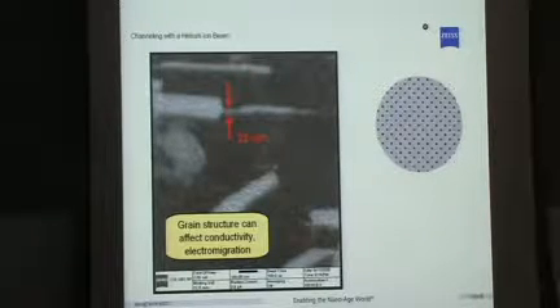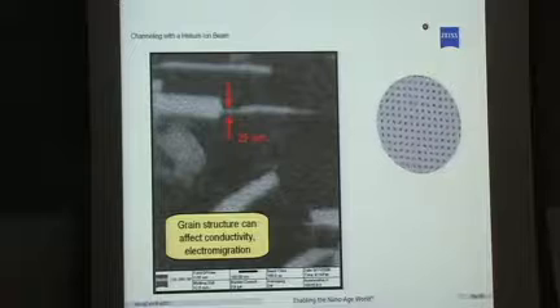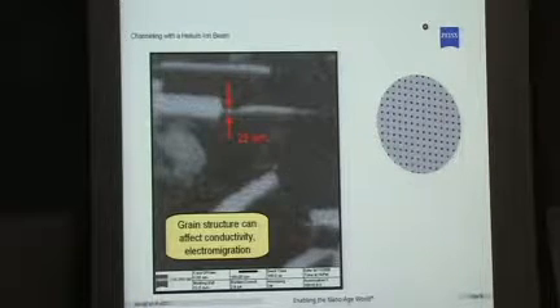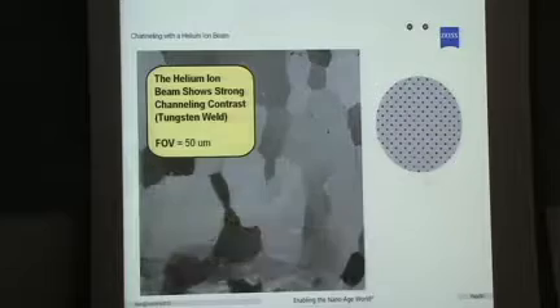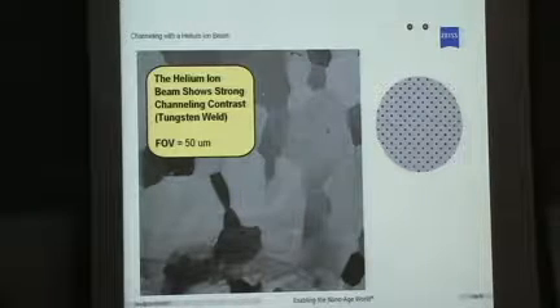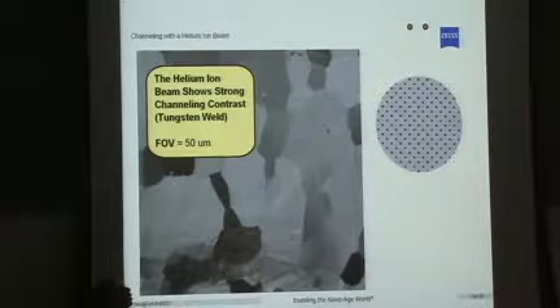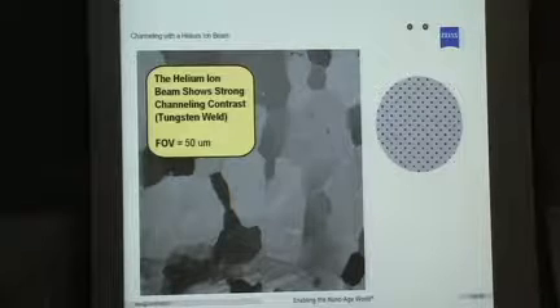But if we rotate that sample, so now it's parallel to the trajectory of the helium beam, you can see it can pass quite elegantly. It goes through without producing a lot of damage. So that would be a darker region. So that's that channeling contrast that you can get with a helium ion beam, which is very interesting if you're studying very small grains.